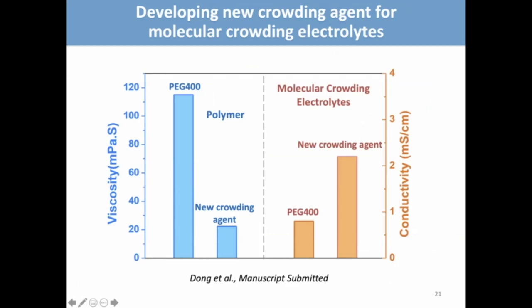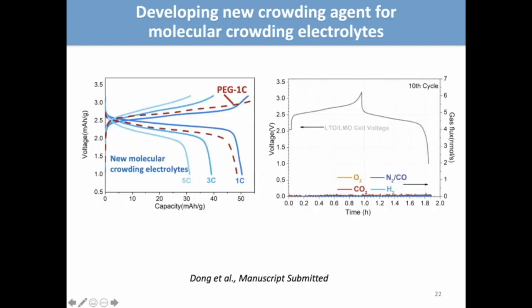If you look at the viscosity, PEG is significantly higher than the pure electrolytes. Therefore, we are developing a new type of crowding agent with significantly lower viscosity to improve this ionic conductivity to more than 2 millisiemen per centimeter. And so that will help us to improve the electrolyte conductivity and also the contact resistance of the cell.